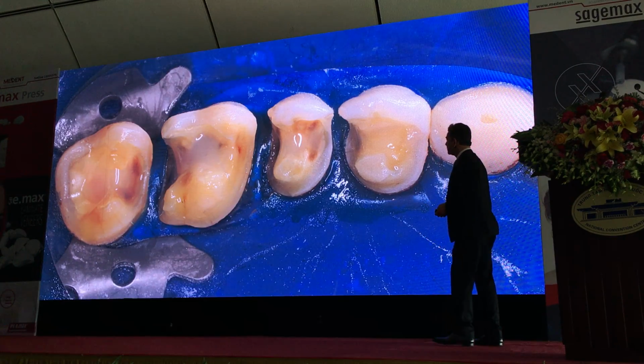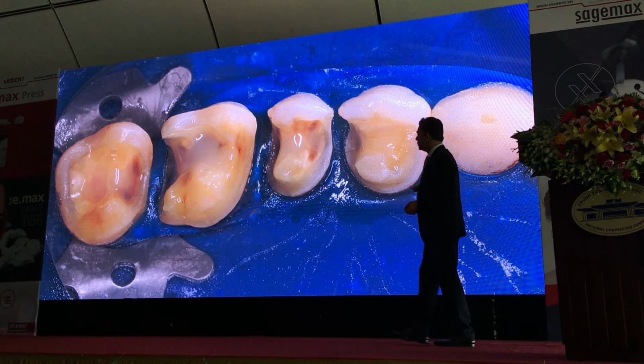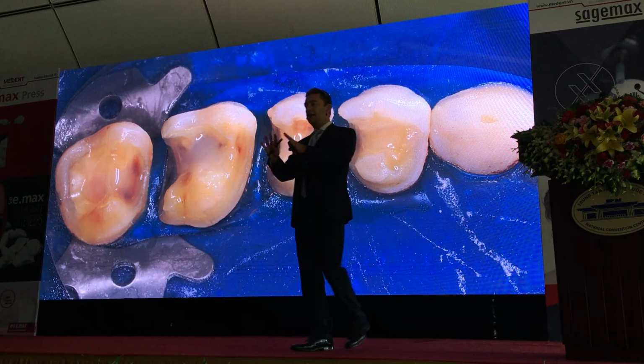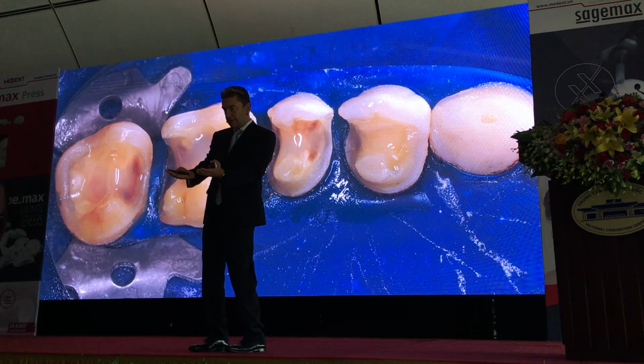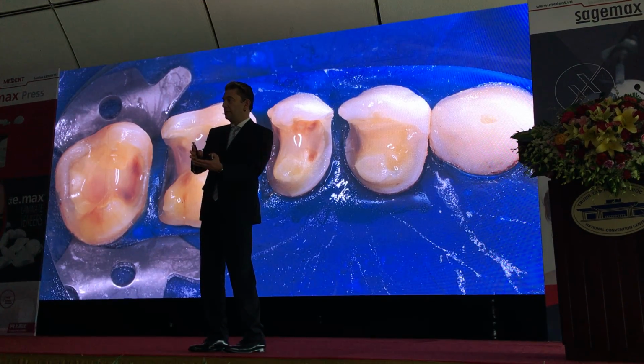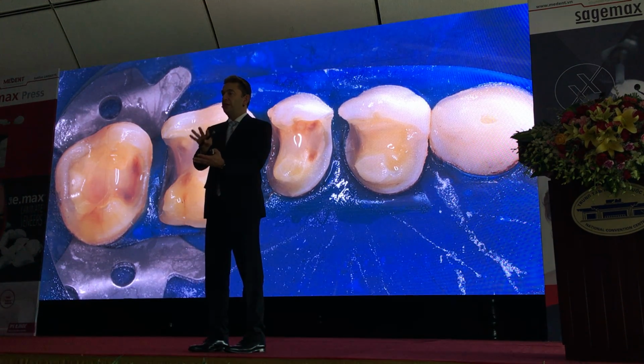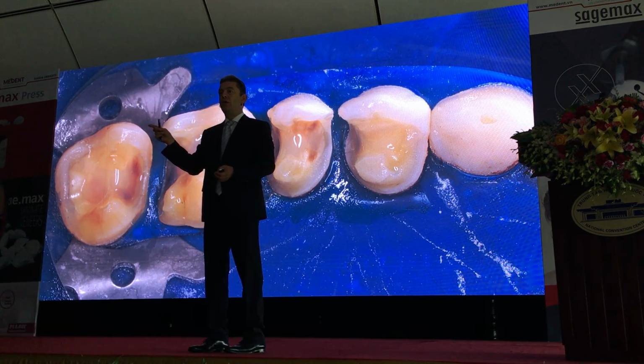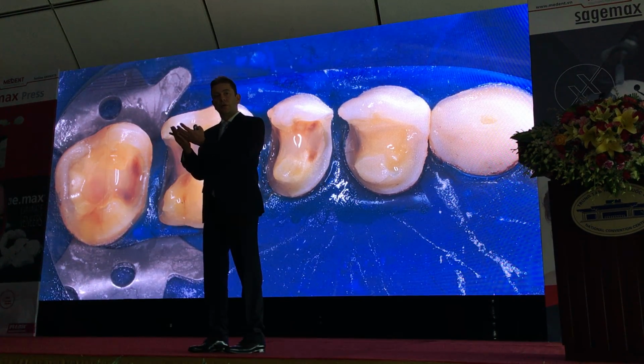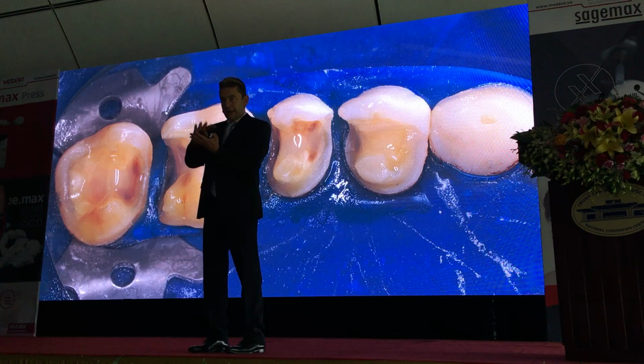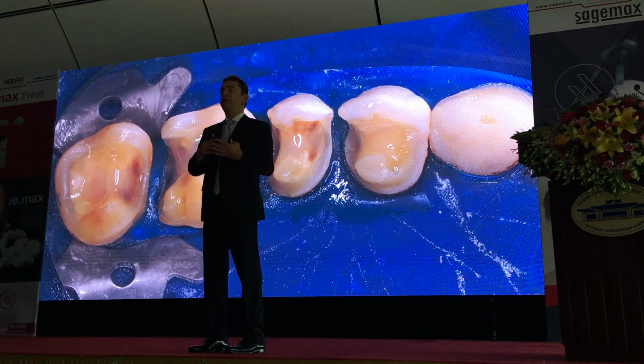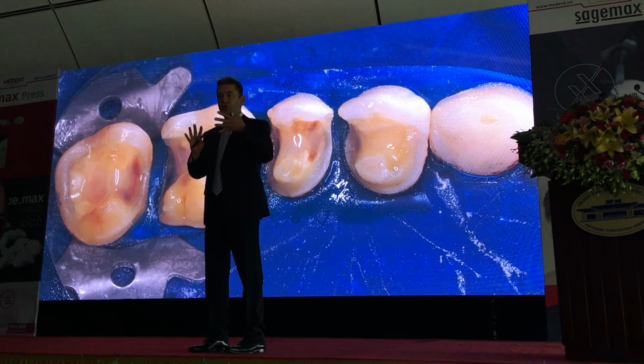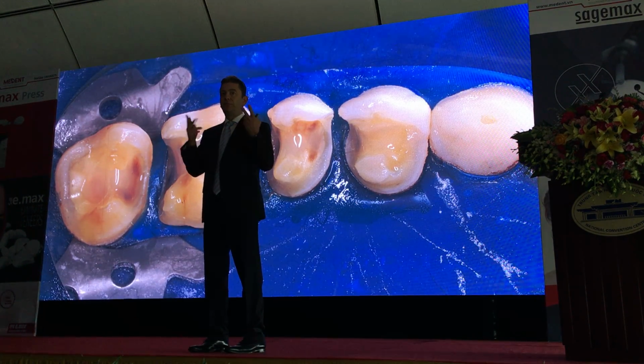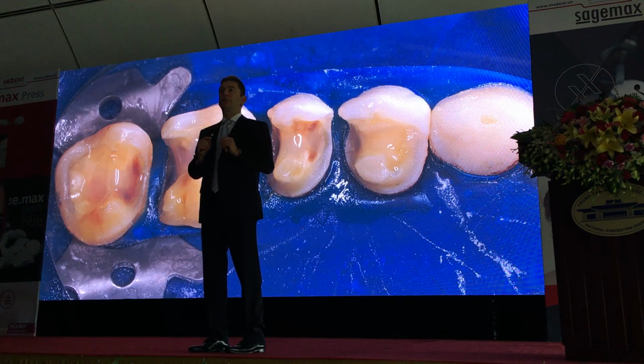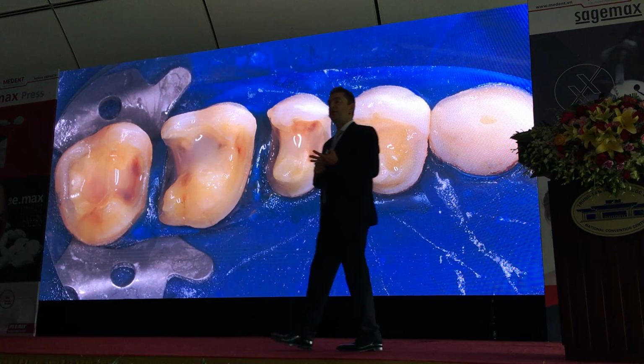Good. And if you have some undercuts now, very often, especially when you are removing old amalgams, you have undercuts, right? So you should block out the undercuts. If you don't do this, the dental technician will block out the undercut on the model, on the die. But then the problem is when you are getting it back, all the undercut will be filled with resin cement, which will then shrink. So it's not a good idea. It's better if you block out the undercut with a resin.